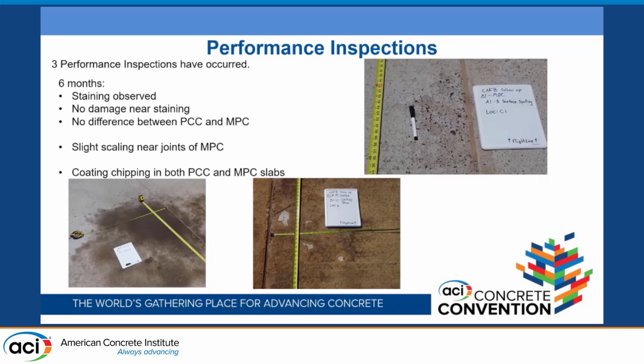So that was done in 2021. Went out and did the first inspection 6 months later. There's been 2 more subsequent inspections, so 3 total. So at 6 months, there was staining observed, no damage near staining, no difference between the PCC or MPC, slight scaling near the joints of the MPC, and then coating chipped on both the MPC and PCC.